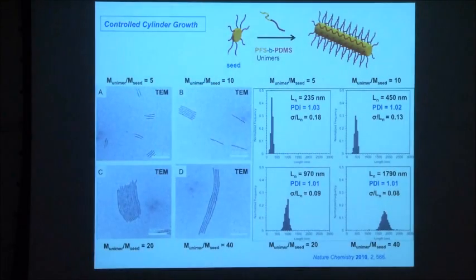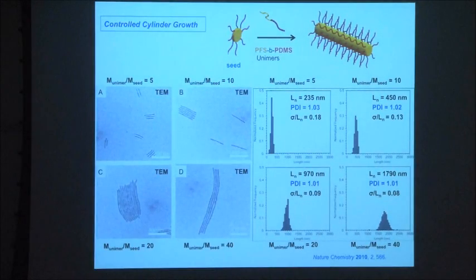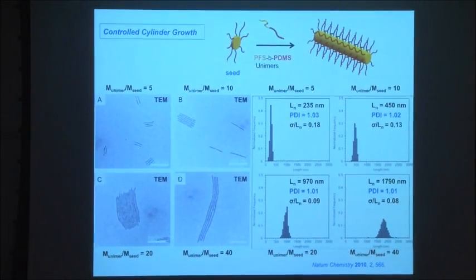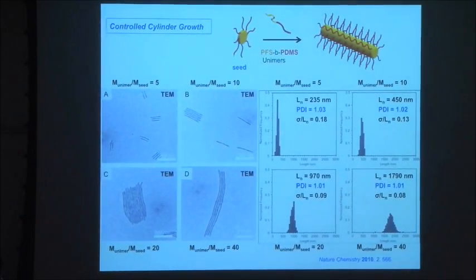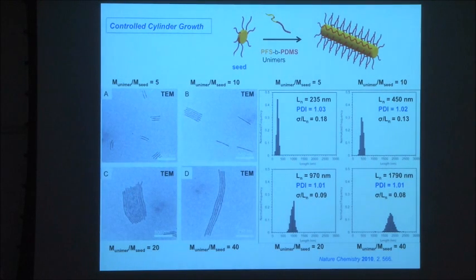Let's take an example. I think this one probably is good. So this is after solvent evaporation. So when you remove the solvent, the micelles have a choice. They can either interact with the surface or they can interact with each other, and they prefer to, I think, interact with each other. So here they're interacting through the coronal blocks, and so this bundling is the TEM.